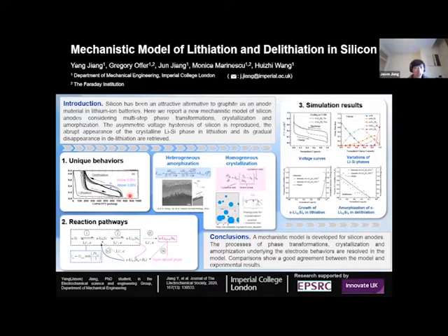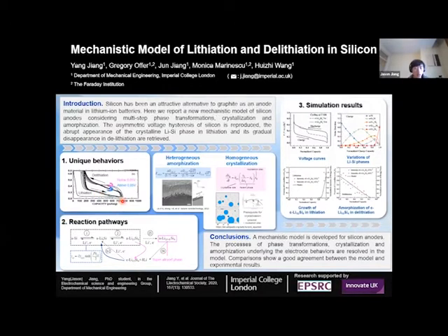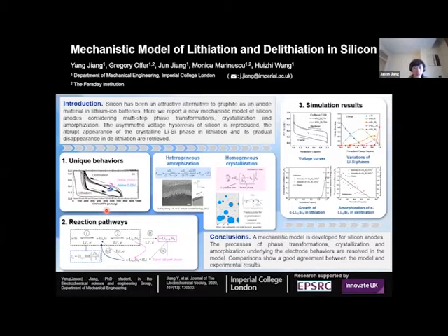In addition, in the latter case, there is a crystalline Li-Si phase — that is, Li15Si4 — which grows very abruptly at the end of the lithiation process. While in the reverse process, this crystalline phase disappears not instantly but very linearly with time during the delithiation process. These unique behaviors stimulated our great interest.